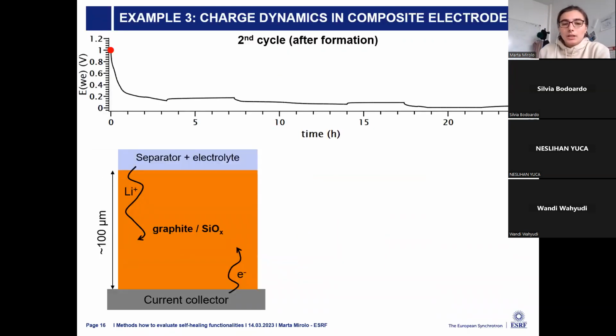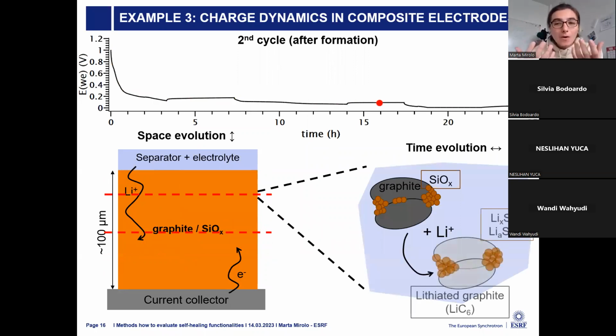And that's exactly what we did in this example, in which we are investigating the graphite silicon oxide composite electrode during battery operation. So we are lithiating the composite, we have some relaxation step, and we want to know what happens in the different parts of the electrode. So we have a thick electrode, we want to know what happens close to the separator, close to the current collector, but we also want to know how the graphite and silicon are evolving in time. So during battery operation, we want to know where the lithium ions are, what they are lithiating.